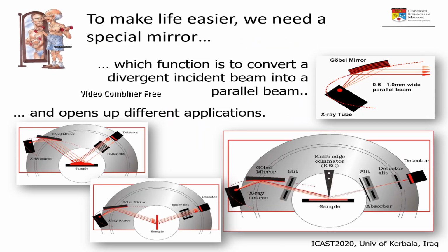To execute this technique of measurement, it is advisable to use a parallel incoming X-ray beam. To convert the divergent X-ray beam into a parallel beam, a special parabolic mirror is required. Interestingly, the use of parallel X-ray beam geometry opens up different types of application, such as transmission mode, reflectometry, and high resolution X-ray diffraction.